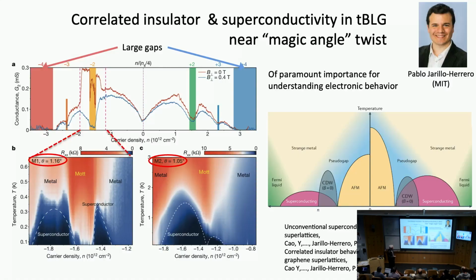So here's the phase diagram of high temperature superconductors, the cuprates and related systems. So there's a superconducting dome here and here. The horizontal axis again is doping, a number of electrons or holes. The vertical axis is temperature. The yellow regions are labeled AFM. This stands for antiferromagnetism, but it is equivalent to saying that in these yellow regions, the system is an insulator. But there are also more interesting phases here in the high temperature superconductors, a charge density wave phase here, a phase called pseudo-gap, another one called strange metal, and so on. And out here, the green regions are the normal metallic behavior referred to as Fermi liquid. Okay, so we don't know if all these phases also exist here, but the basic structure is there: superconducting domes separated by an insulating region. Here's the insulating region and other metallic kinds of behaviors.